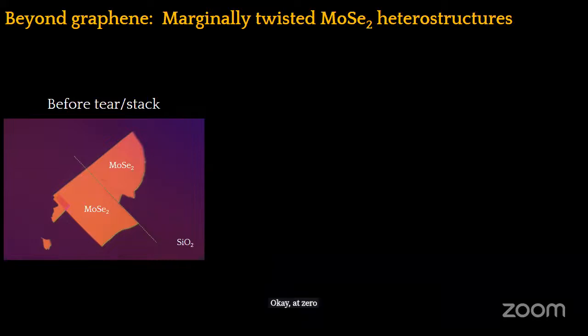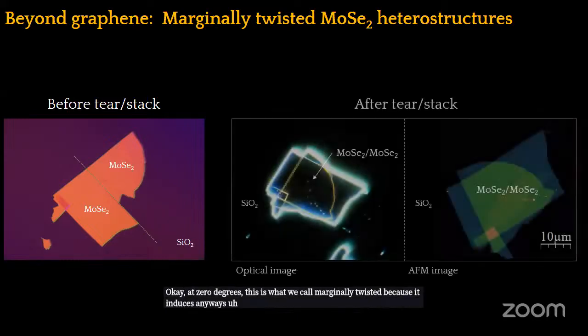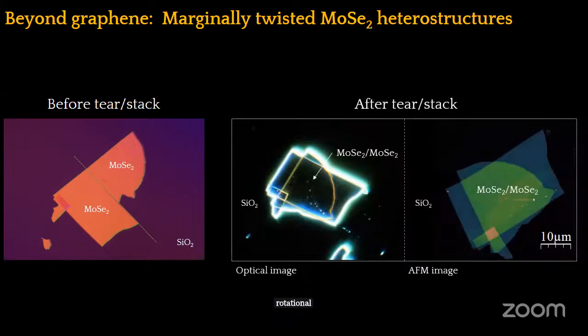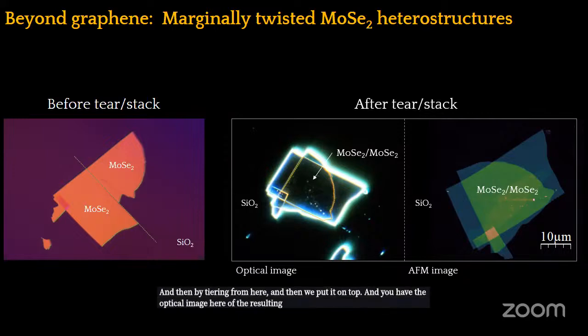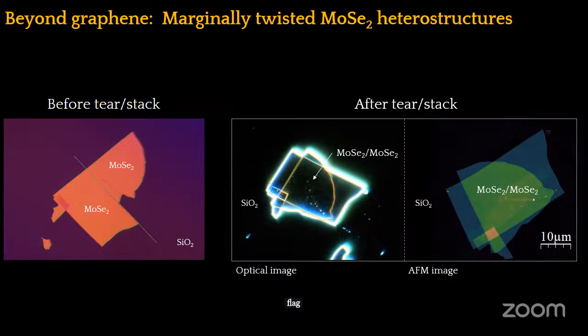This is what we call marginally twisted because it induces anyways a rotational disorder, even if you stack them at 0 degrees. So basically what we have done here is to pick up this flake and then by tearing from here, we put it on top. And you have the optical image here of the resulting flake and the corresponding AFM image that shows the resulting heterostructure.